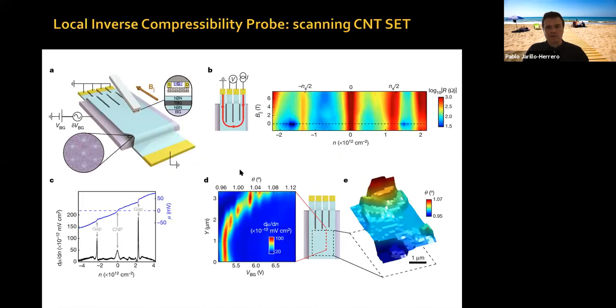So let me tell you about our experiments. These are experiments where the group of Shahal Ilani has a scanning carbon nanotube single electron transistor. Basically, it is a local, very sensitive charge detector, or electric field detector, voltage detector. So we have our magic angle graphene device here. We have a back gate. We have the scanning SET, which is a very short nanotube, so it has a large charging energy when you cool down. This gives it extreme sensitivity to electric fields. So now you're varying the back gate and you're measuring the response on your SET as you vary the density of carriers in the graphene, and then you see what the effect is. You can also do transport in this device.